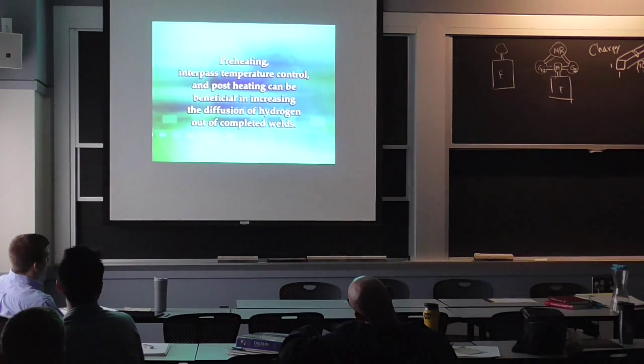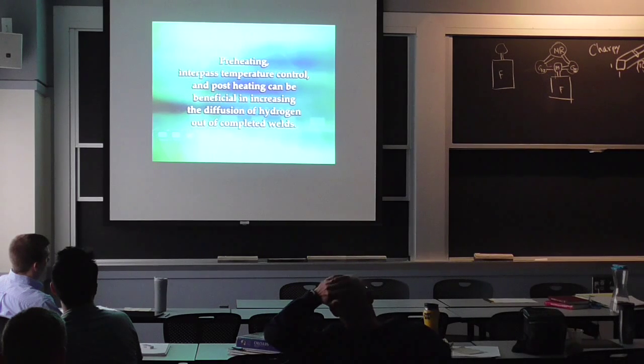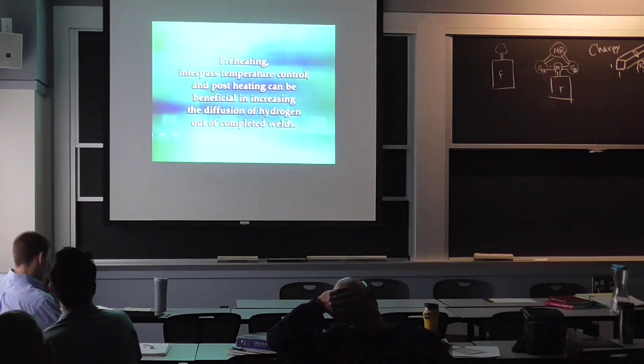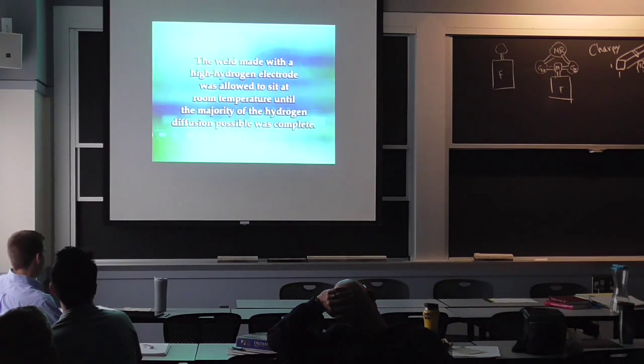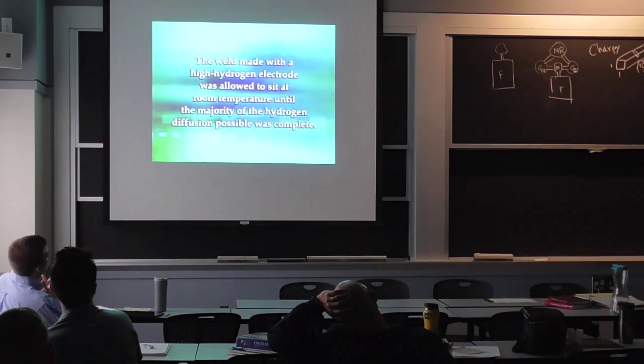Preheating, interpass temperature control, and post-heating can be beneficial in increasing the diffusion of hydrogen out of completed welds. The weld made with a high hydrogen electrode was allowed to sit at room temperature until the majority of the hydrogen diffusion possible was complete.